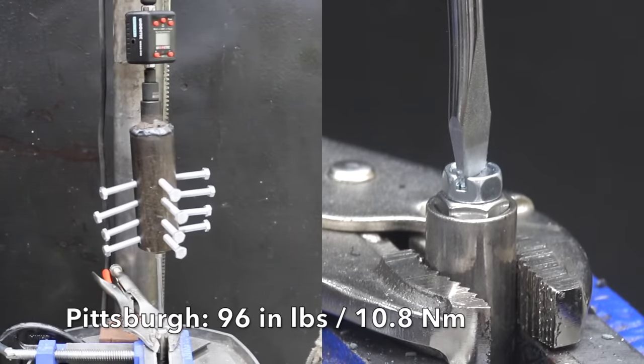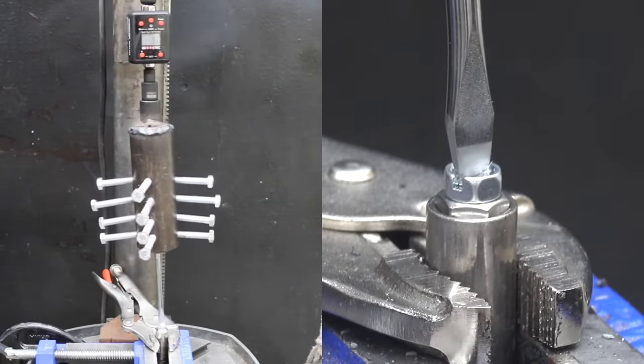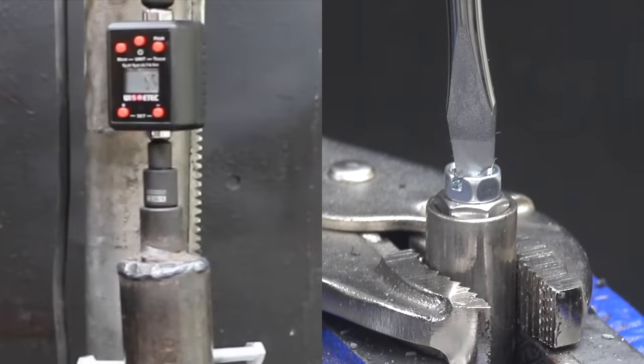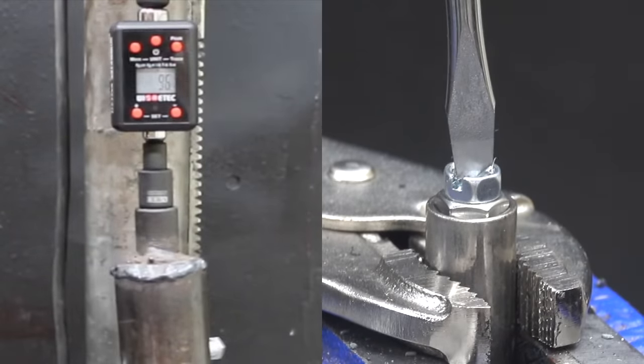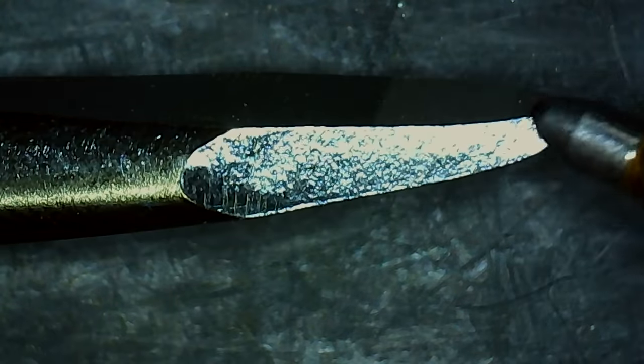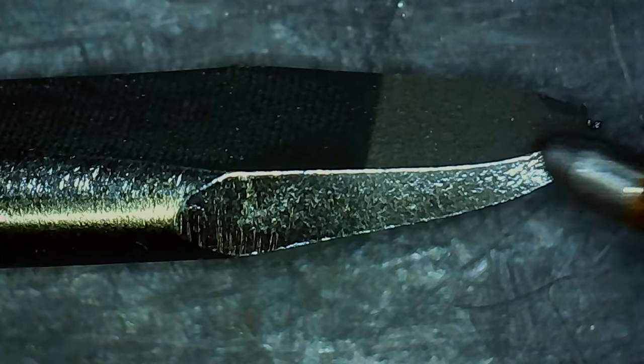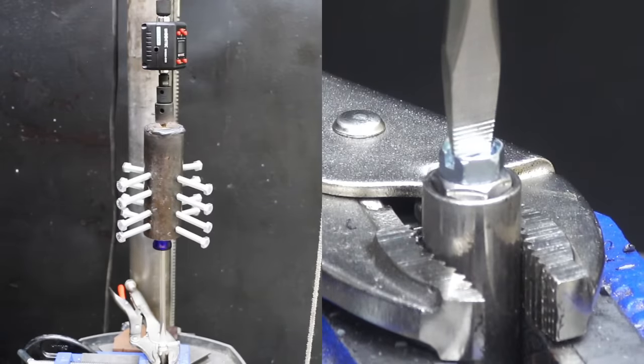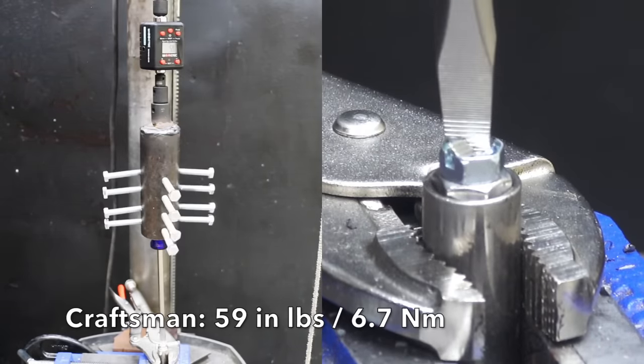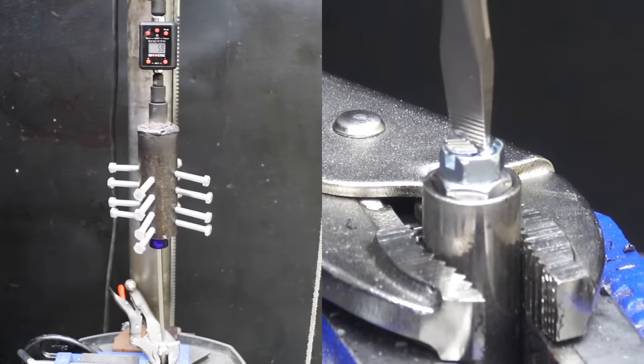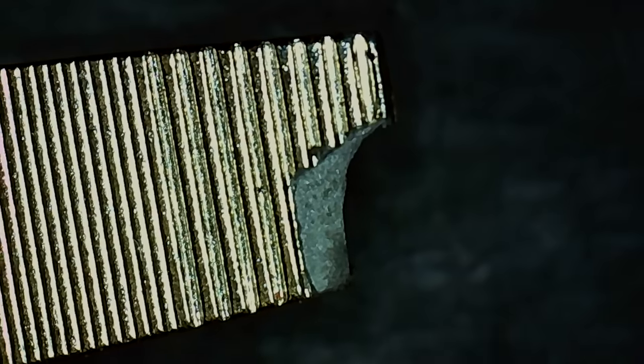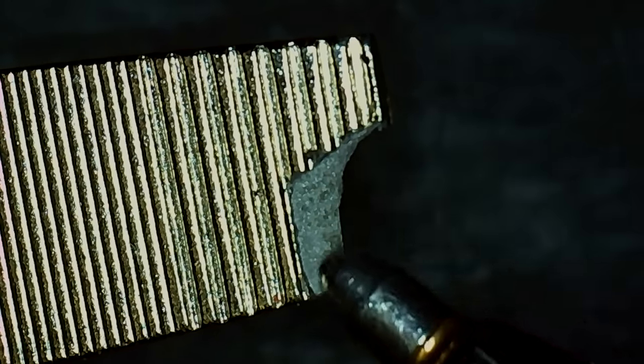Let's test the Harbor Freight Pittsburgh brand first. And the Harbor Freight Pittsburgh blade is quite a bit thicker than a lot of the other brands at 1.15 millimeters. And the screwdriver actually performed fairly well at 96 inch pounds, but the blade is pretty badly bent. And the Craftsman has a much thinner blade than the Pittsburgh at only 1 millimeter. And the Craftsman blade is very brittle and it broke at only 59 inch pounds. However, the Craftsman does come with a much larger screwdriver in the screwdriver set.